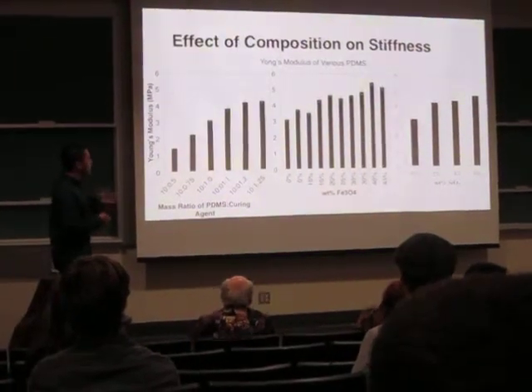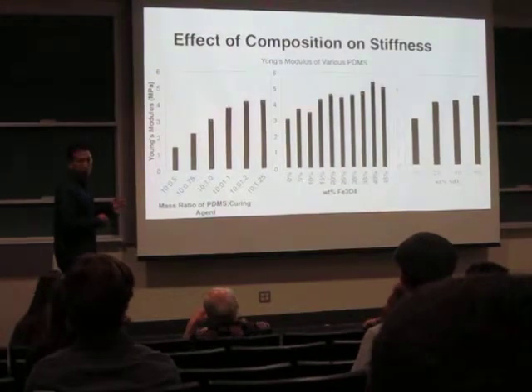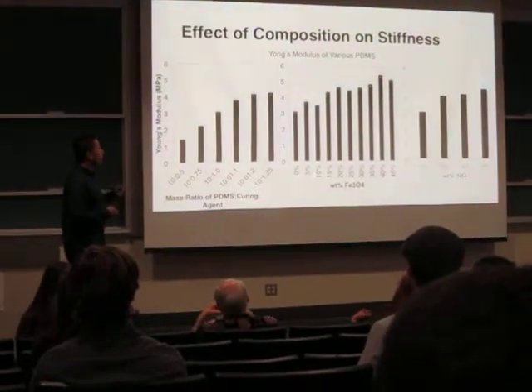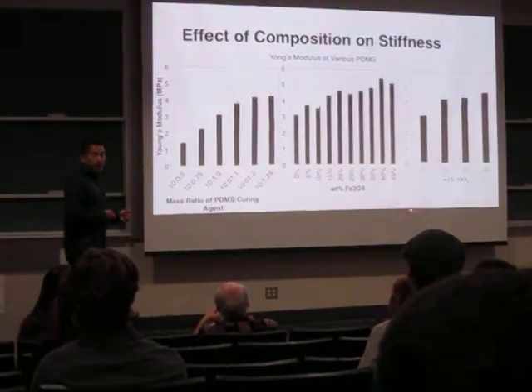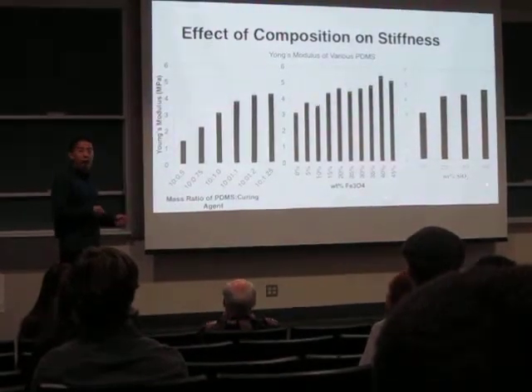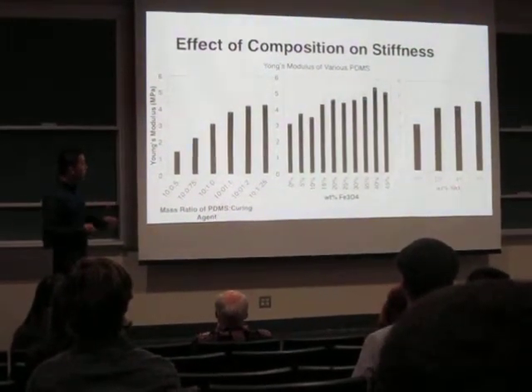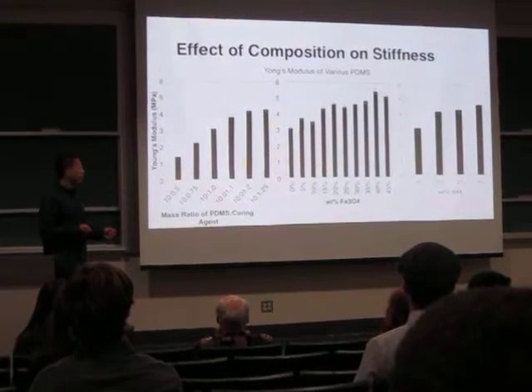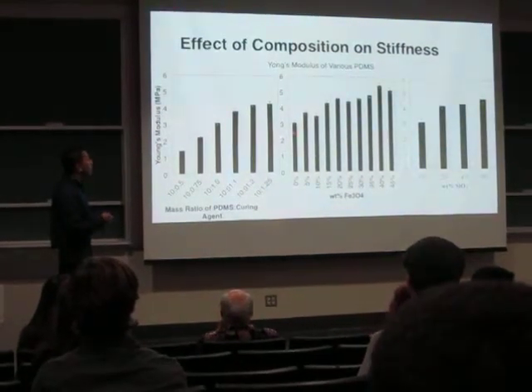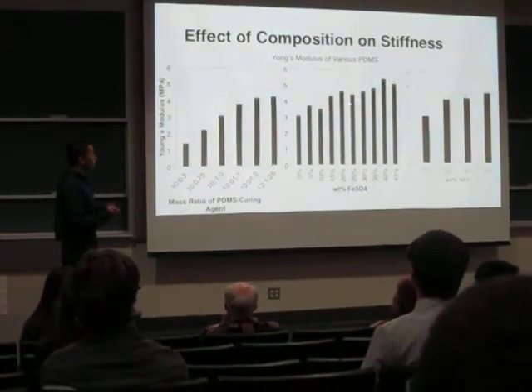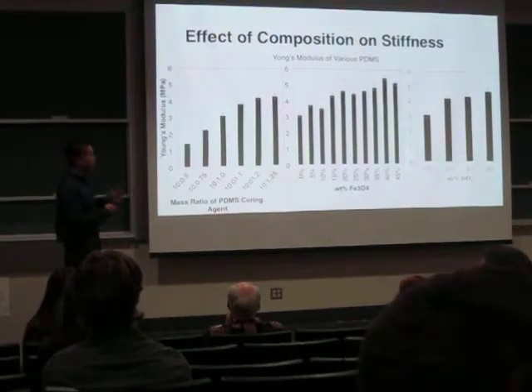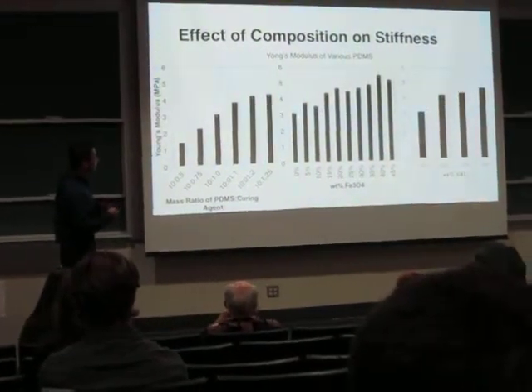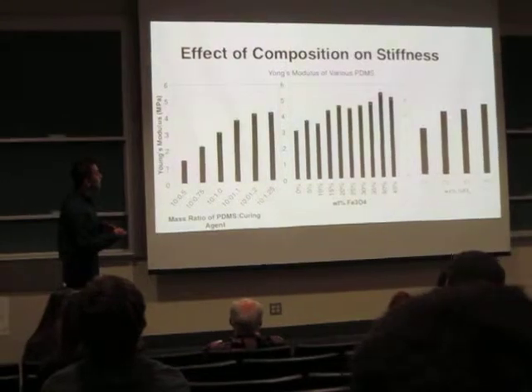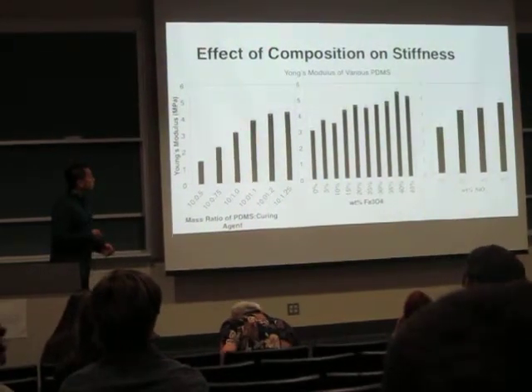And also we can increase the strength of the material by adding particles. What we have done is adding black iron oxide, which has a size of about 1 micron, and also silica particles with a size of 7 nanometers. And with both, we can see the strength is increased. Not a lot, but you can clearly see the trend. So this is black iron oxide, and this is the silica particles.